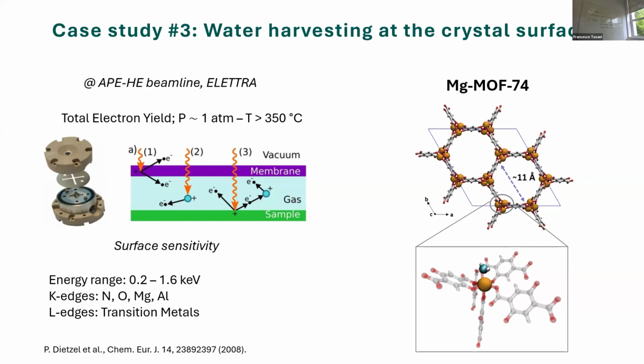For example, there's a detection mode called total electron yield, TEY. This is based on the fact that the incoming photons go through an X-ray transparent membrane. They hit the sample at a certain point. The sample emits electrons, almost similar to an XPS process. And then you have the progressive release of electrons, and these electrons are measured as a drain current. This process, of course, is intrinsically surface sensitive. So soft XAS measured in TEY mode will be sensitive to about 5 to 10 layers below the immediate surface.